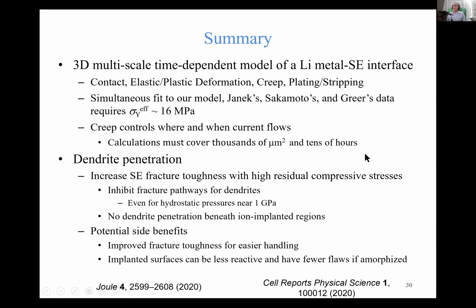So to summarize my talk, there were two parts. In the first part, I said that we were going to build a three-dimensional multi-scale time-dependent model of a lithium metal solid electrolyte interface. And we incorporated contact, the difference between electrical and mechanical contact, elastic plastic deformation. We're assuming perfect elastic, perfectly plastic. We incorporated creep, plating, stripping, and we used all of the mechanical properties taken from Michigan, except yield strength.